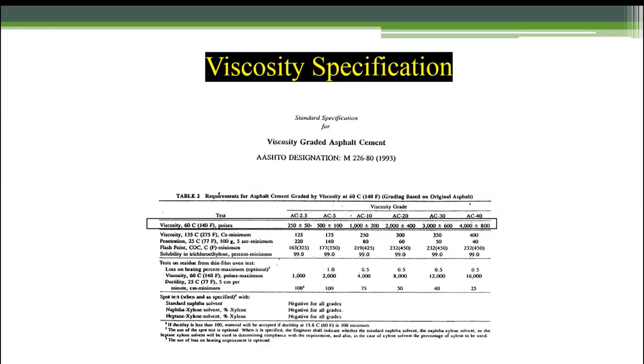So for example, when I was in Wyoming with the Wyoming DOT, both in materials lab and as resident engineer, the standard kind of working grade asphalt we used was AC 20. What does AC 20 mean? Well, that's 2,000 Poises plus or minus 400. So essentially 1,600 to 2,400 had to be the viscosity measurement. And that's a fairly hard asphalt, fairly stiff.